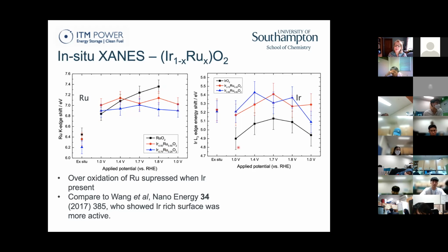If we look from the perspective of the iridium, for the iridium oxide only catalyst, first of all, it doesn't change oxidation state much itself. Its oxidation state is a bit different when it's mixed with ruthenium. So we are getting some electronic interaction between the ruthenium and the iridium, which might account for the enhanced activity of the iridium atoms in the mixed material. Their oxidation state is different, but it doesn't change very much